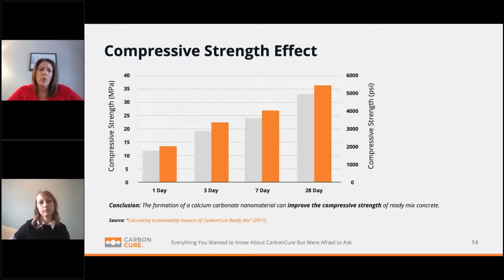So there's about 0.2% of the cement that is going to react with the CO2 that we're injecting, and that's what forms the nanoparticles or the nanominerals, while the remaining 99.8% of the cement will continue to undergo normal hydration, but there'll be that enhanced efficiency thanks to the nanominerals. So more efficient cement means a higher strength.